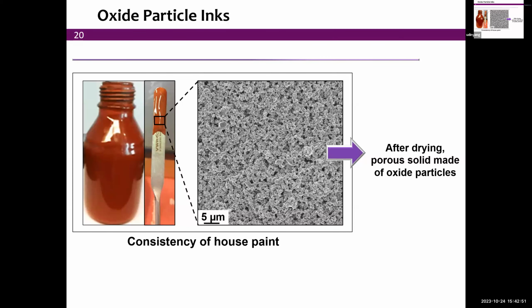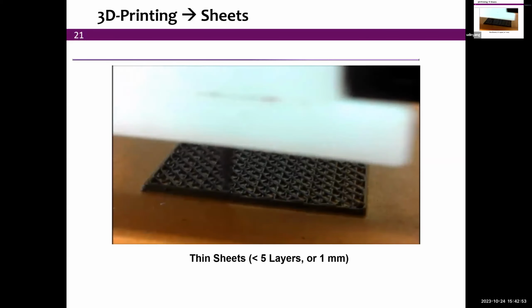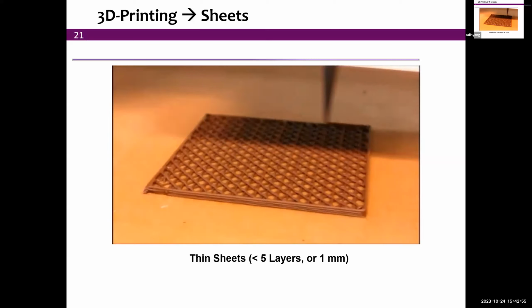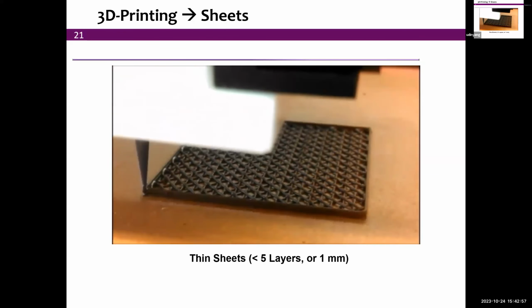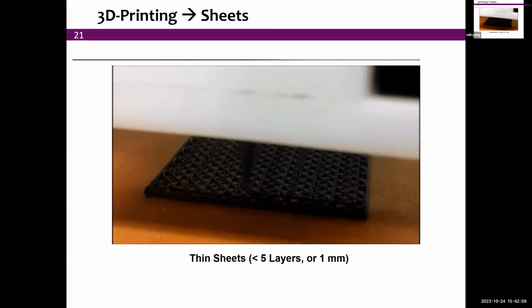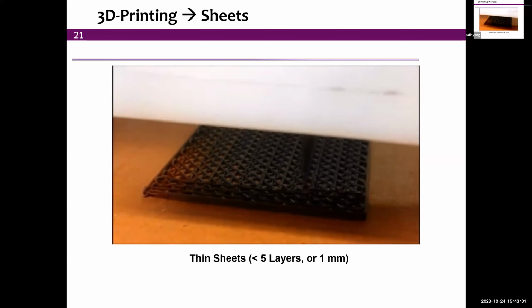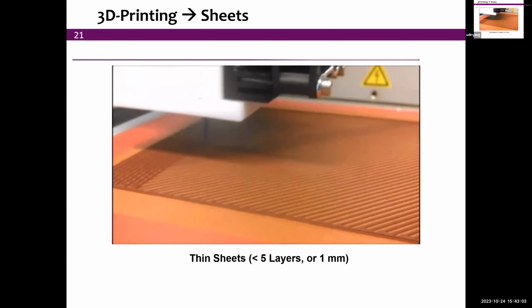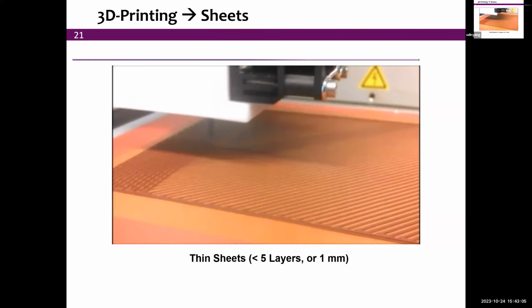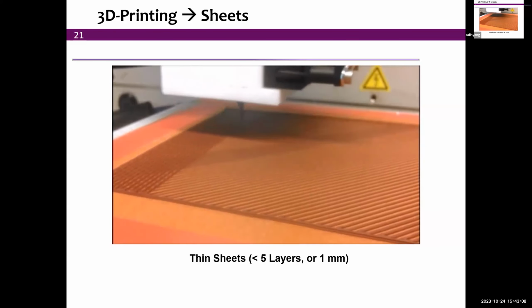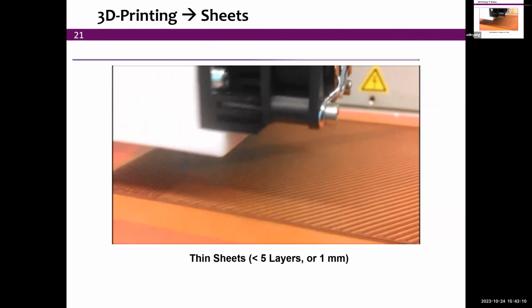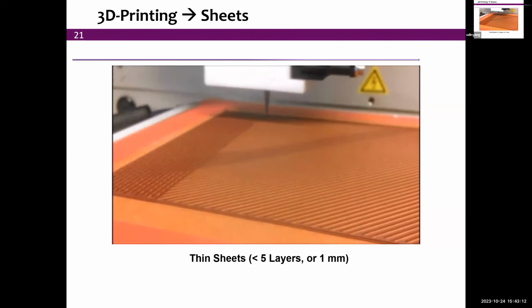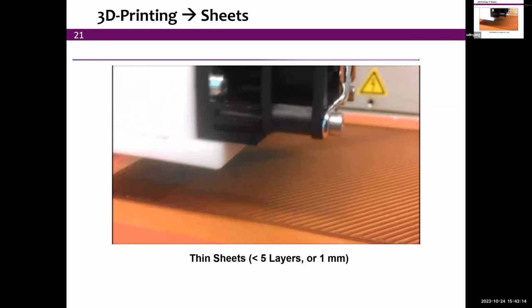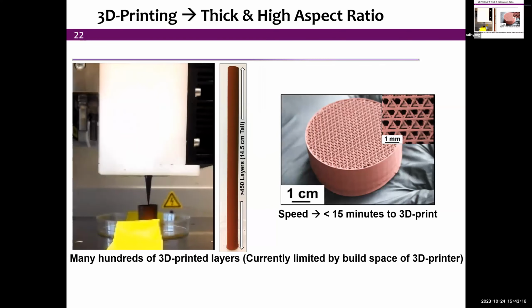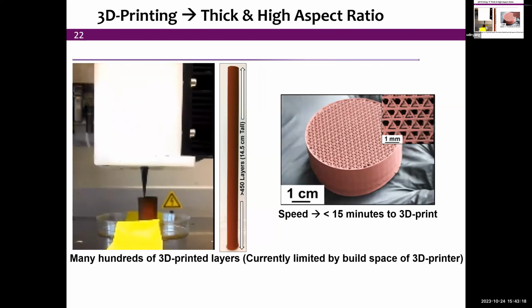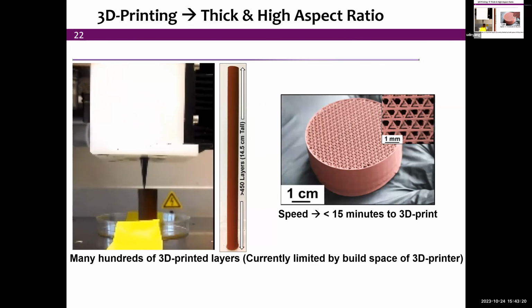And this is the kind of viscosity that we have in paint. So it's very inexpensive if you think of it. You need a room temperature polymer 3D printer and a sintering furnace to achieve those. So here's an example of a thin sheet, 5 layers only. We can make it quite big, as you can see, and we can use those thin sheets to create 3D structures by cutting and bending, so origami and kirigami in principle. I'll show examples. Or you can make extremely long structures, this is again, of course, accelerated.